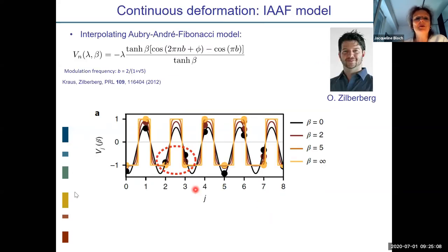Then there was a very interesting mathematical proposal by Kraus and Zilberberg in 2012, which says that you can find a magic formula, which depends on lambda and on a new parameter called beta, which allows you to continuously deform the Aubry-André quasicrystal into the Fibonacci. When beta equals zero, you see this black potential. This is the Aubry-André one. Then as beta grows and goes to infinity, you see that the potential becomes steeper and steeper. And for beta equal infinity, you have only two values and you recover the Fibonacci potential.